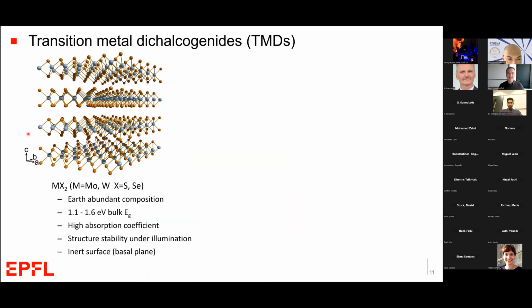Okay, I can switch gears a little bit to a related system. Another system that's been in development in our lab now for a few years is based on these transition metal dichalcogenides of the form MX2, for example, molybdenum sulfide or tungsten diselenide. So this class of materials has been known for a long time as promising materials for solar energy conversion because they're essentially earth abundant. They have good band gaps for solar energy conversion, high absorption coefficients, and they're really, really stable. In fact, molybdenum sulfide is used as a high temperature tribological material, in particular because of its layered structure. It has lubrication properties as the layers can slide past each other when they're under high shear stress, similar to a material like graphene.